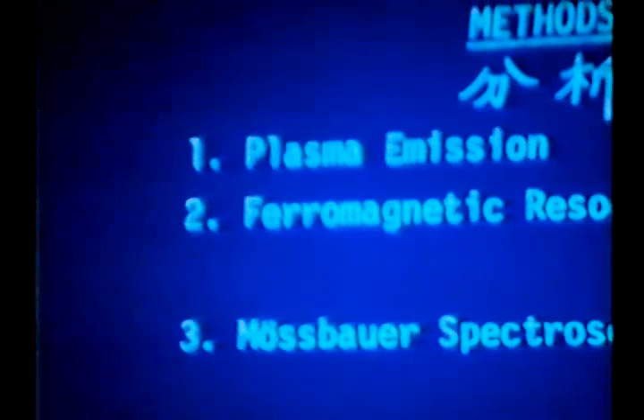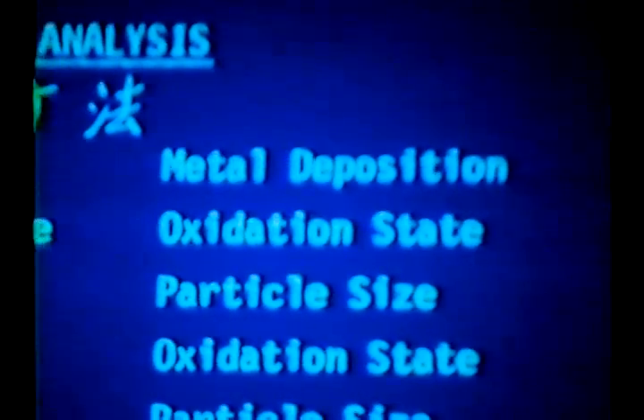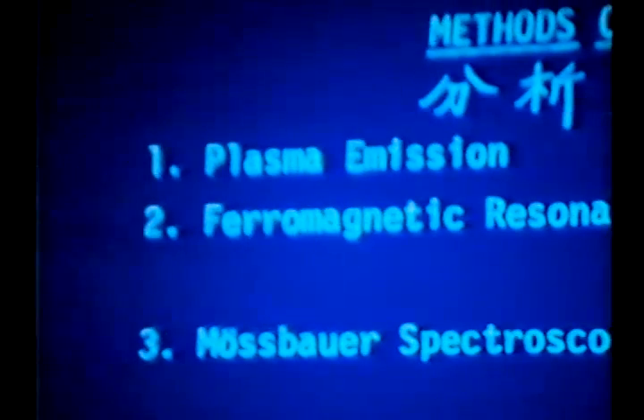If you think you've made a real small metal cluster in a zeolite, and you think it's 5, 10, however many angstroms, the real tough part has just begun. You've got to try to prove that's what you have. And that's not an easy thing to do. And that's why we really chose iron and cobalt. It's easy to look at those with lots of different techniques.